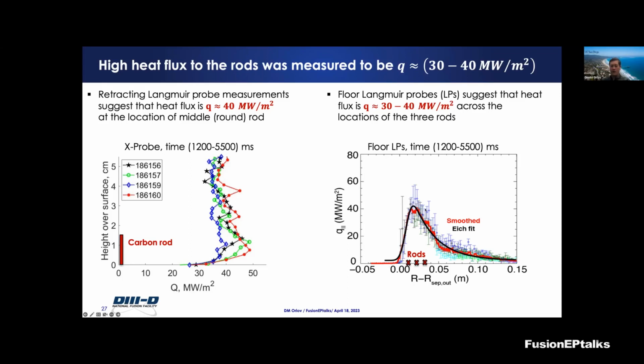The red profile is the smoothed fit to the Langmuir probe data for the heat fluxes, shown on the y-axis, with distance from the strike point on the x-axis in meters. The black one is the typical ITER fit you're probably familiar with. Both plots agree that the carbon rods experienced about 40 megawatts per meter squared heat fluxes where they were in the edge of the plasma region.